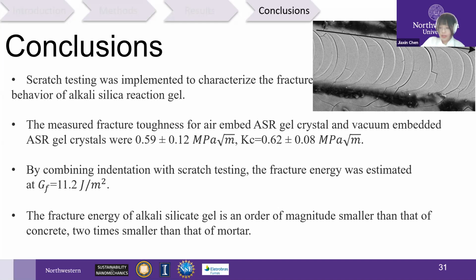The fracture energy of alkali-silica gel is an order of magnitude smaller than that of concrete and 2 times smaller than that of mortar. I will end my presentation with our scanning electron microscope image of the ASR gel crystal fracture surface on the top.